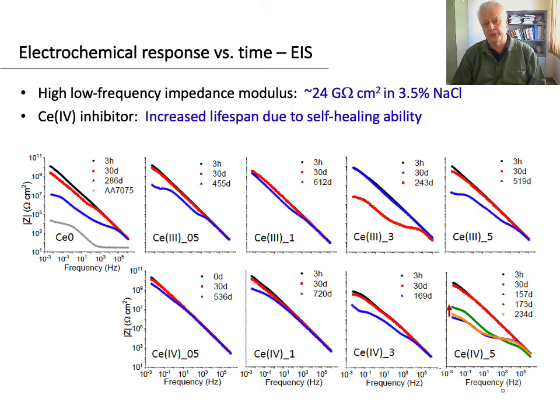Okay, then the coatings were subjected to electrochemical impedance spectroscopy in continuous immersion tests. All coatings showed high corrosion resistance with a low frequency impedance modulus of up to 24 gigaohms, 6 orders of magnitude higher than the uncoated aluminum. In terms of durability, the incorporation of Ce(IV) showed excellent protection, providing a passive barrier of more than 600 days obtained for the Ce(IV)_1 coating.